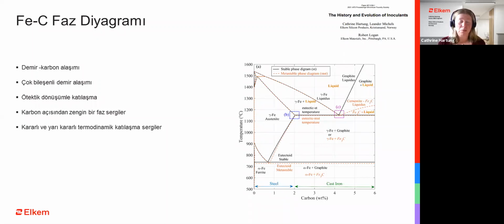So in cast iron, you can dissolve up to 2% carbon in the iron matrix. And this is where cast iron and steel deviate, where steel is predominantly an iron phase. The cast iron has two phases. It has an iron-rich phase, which at the temperature of solidification we call austenite, and then it has a carbon-rich phase, which is making cast iron the interesting and maybe also tricky material, and also why inoculation is so important. So the cast iron solidifies with a eutectic transformation, which you see here in the pink frame. And we will take a closer look at this eutectic point in the next slide.